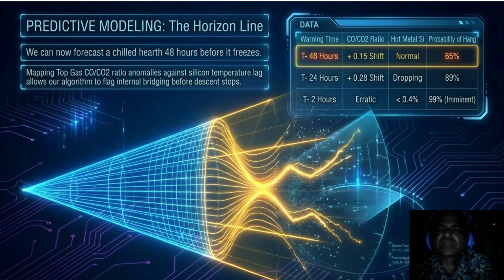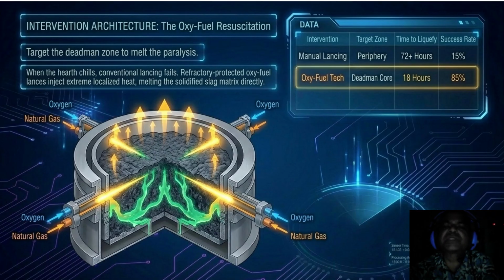By T minus 24 hours, that probability jumps to 89% as silicon starts dropping. If you wait until T minus 2 hours, when the gas is erratic and silicon is below 0.4%, failure is 99% imminent. So the operational impact here is the power of preemption. 48 hours is enough time to adjust the burden and prevent the catastrophe. If you wait for the symptom to show up in the iron, it's already too late. But if the worst happens and the hearth does chill, we need a modern intervention architecture to bring the furnace back to life.